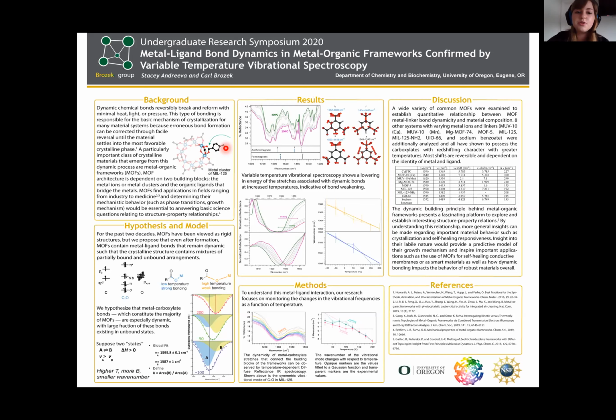Therefore, we came to the conclusion that rigid bonding cannot explain MOF behavior. So we propose that this behavior could be visualized by observing the association and dissociation between the metal and the carboxylate, I mean this part, and by infrared diffuse reflectance spectroscopy. So we focused on observing changes in the carboxylate driven by the temperature, and due to the weakness of these bonds, we can see here in the model section that increasing the temperature would also increase the population of the state of unbound species. And so variable temperature vibrational spectroscopy would therefore show the lowering in energy.